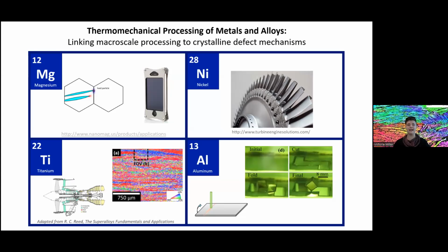Now, along those two lines, bridging the mesoscale gap and developing infrastructure for ICME, we work in a lot of material systems. We work in magnesium, trying to look at how the microscopic deformation mechanisms result in brittleness so that we can avoid brittle failure. We look at nickel superalloys to make turbine engine disks that can operate for longer times at higher temperatures. Similarly, we're interested in titanium, also for gas turbine engines. And then additionally, we have a project on using lasers to form sheet metal like sheet aluminum. So you can see that you can cut and fold all in one laser process to get a nice little cube.